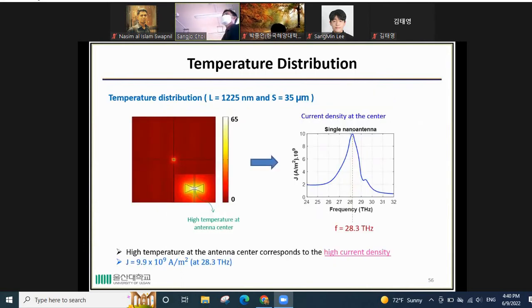And this is the temperature distribution analysis for the optimum parameters. So we can see high temperature at the antenna center, which corresponds to the high current density.